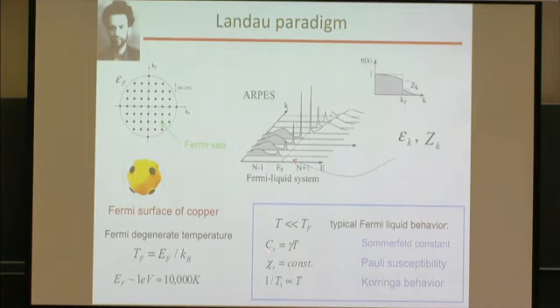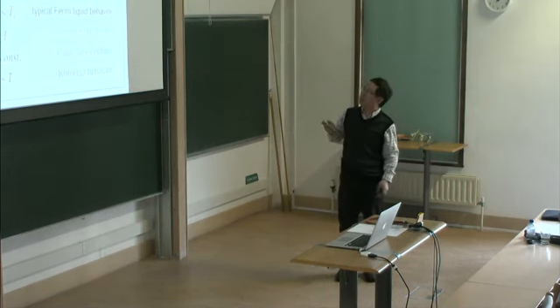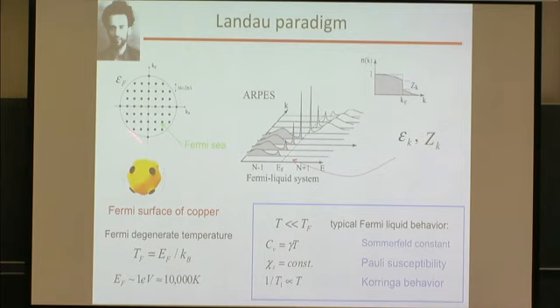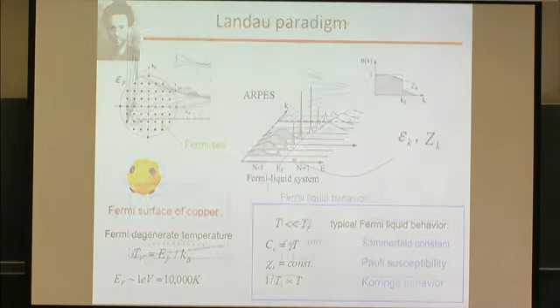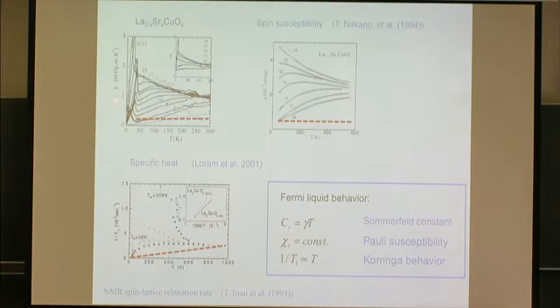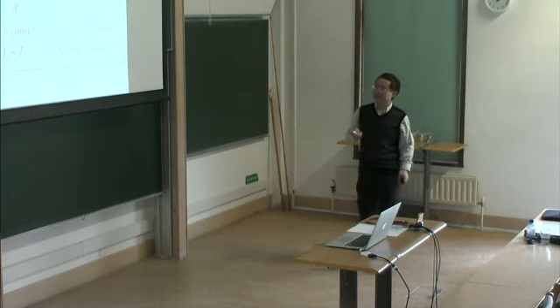For example, specific heat will have a linear temperature dependence, and the Pauli spin susceptibility has constant behavior, or the nuclear magnetic resonance relaxation rate shows a linear T behavior. All these behaviors actually persist when you turn on weak interaction, which will renormalize the excitation around the Fermi surface, and make the momentum jump go from 1 to some reduced value, which is the quasi-particle weight. But for the high-Tc cuprates, this is the Sommerfeld constant. This red dashed line is the Fermi liquid behavior. You see above the superconducting transition temperature, gamma shows a strong temperature dependence, and the different doping concentrations all clearly deviate from this constant behavior.